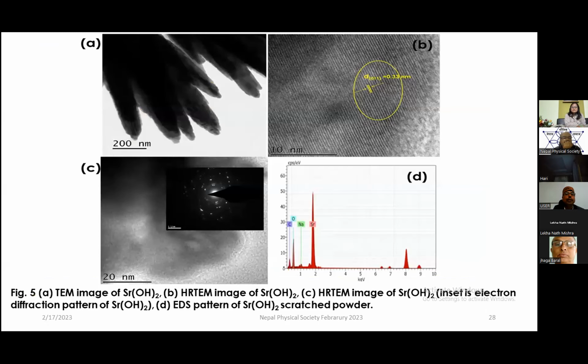So let us go to the HRTEM and TEM images. One can see a very beautiful picture. Figure B shows the lattice fringes with interplanar spacing. The spacing comes out as 0.33 nanometer, which corresponds to the 011 plane of strontium hydroxide, exhibiting the orthorhombic crystal structure. So whatever information we are getting corresponds to the XRD analysis.